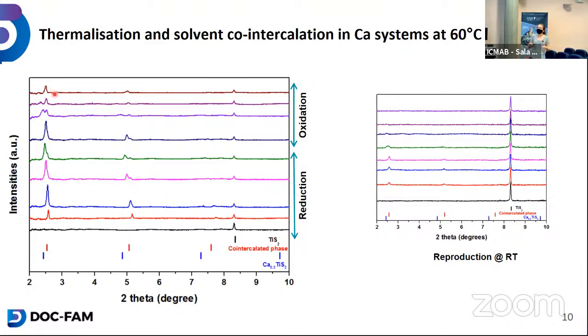So I present here another cell, which was cycled at room temperature. However, this time we were not able to get the calcium intercalated phase. We only have the co-intercalated one. But you can see that it grows during the reduction, and upon reoxidation, it disappears completely, and you retrieve your starting material.